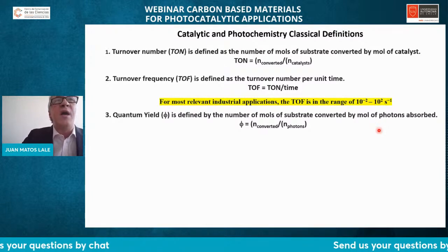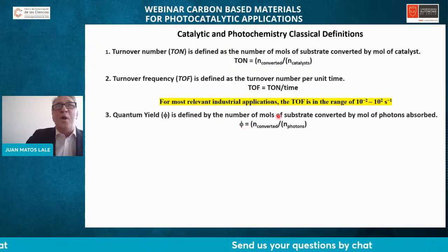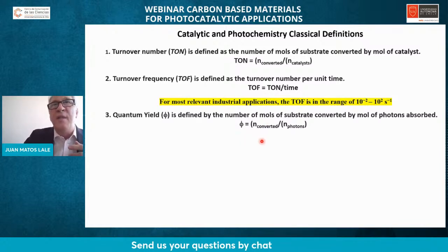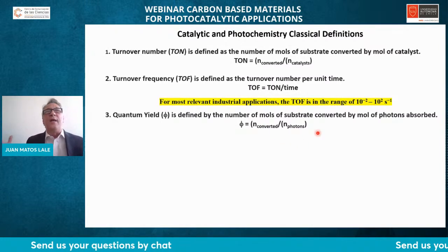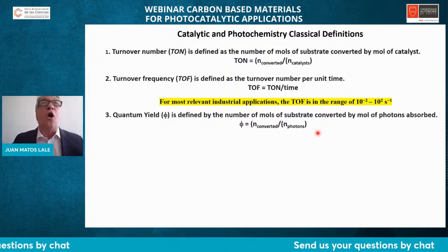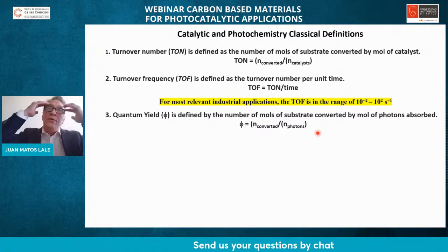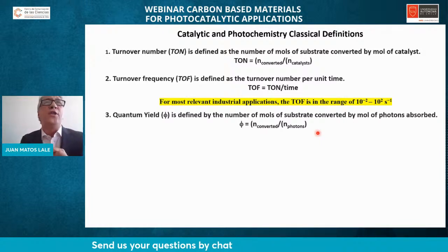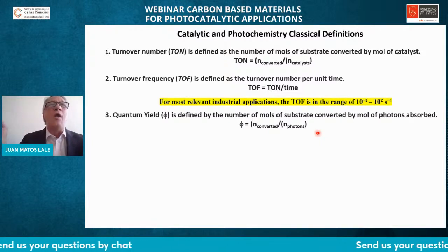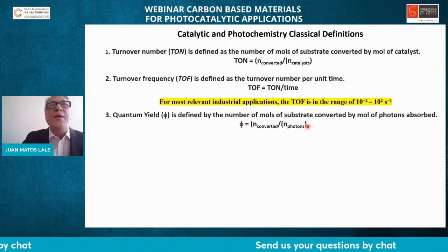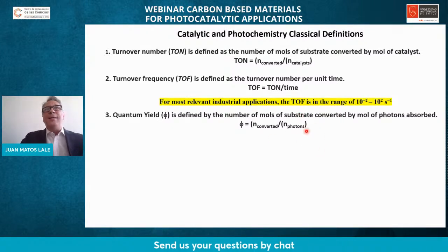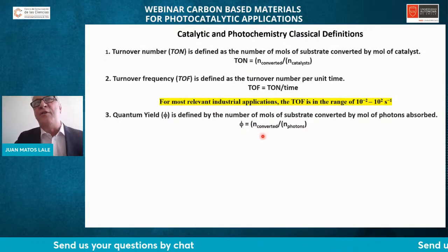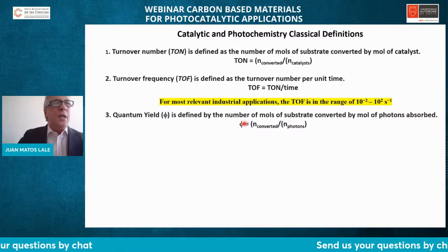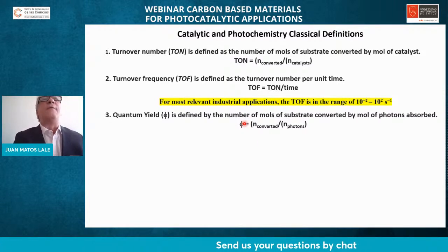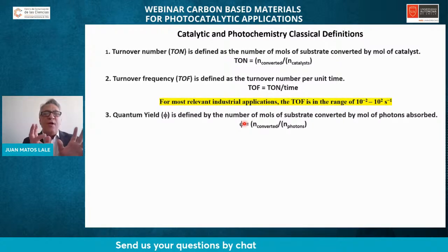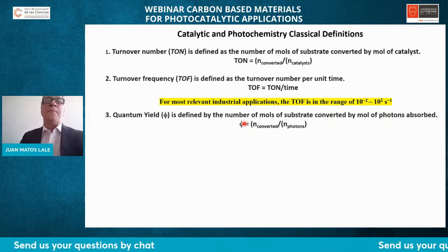At the same time, the quantum yield is defined by the number of moles of substrate converted per mole of photons absorbed. But in the case of carbon materials and dealing with solar irradiation, you can think about the high quantity of photons we have in a real solar CPC photoreactor. This quantity is so high that it doesn't matter that you have a very high converted fraction of reagent. The quantum yield is very poor, and it's not the reality of the reaction rate you are following in your system.